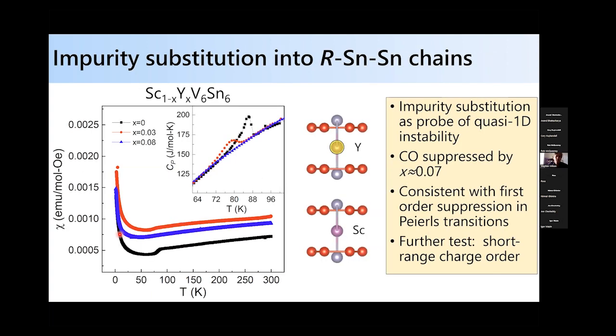So you can test this a little bit more by doing some substitution. You can say, okay, I'm going to replace a little bit of the scandium, which is this much smaller site, with a larger yttrium ion. When you do that and you look at susceptibility as a function of doping yttrium onto the scandium site, you can see that the parent charge order, which is around 90 Kelvin or so, is rapidly suppressed. And maybe that suggests that you have a dominant one-dimensional instability whose coherence is easily interrupted via this substitutional disorder.